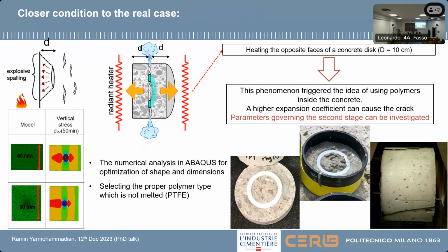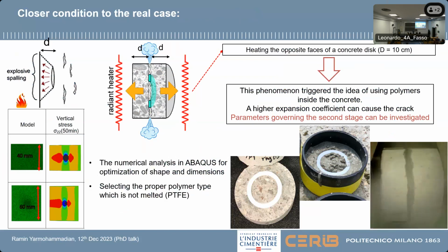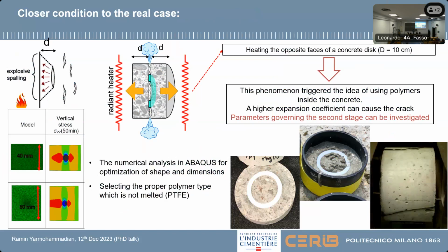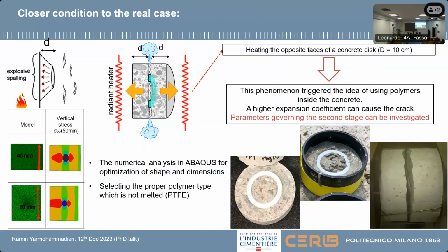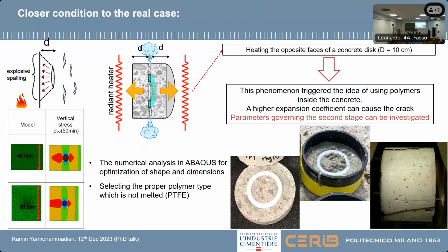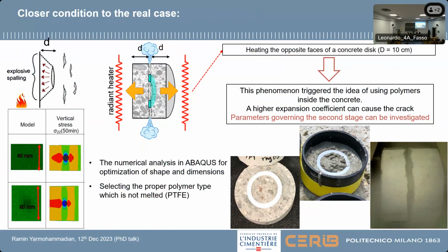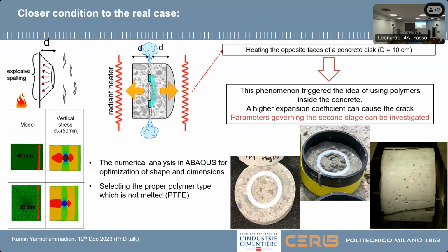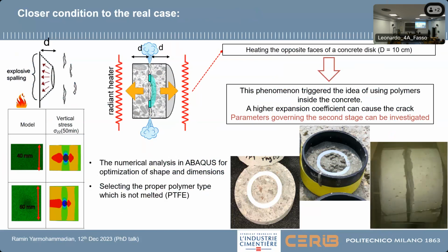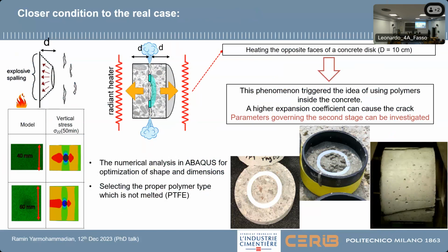So the idea is to fill the first half of the concrete, put the polymer there, and then fill the second half, and then, as you see, we heat from two sides. All of these dimensions and material choices we optimized with Abaqus, using axisymmetric models, and you can see the first spalling that we could get. This is, I would say, the smallest material-scale spalling test that you could see in the world. And then you can see the drop of water which comes out before the spalling.